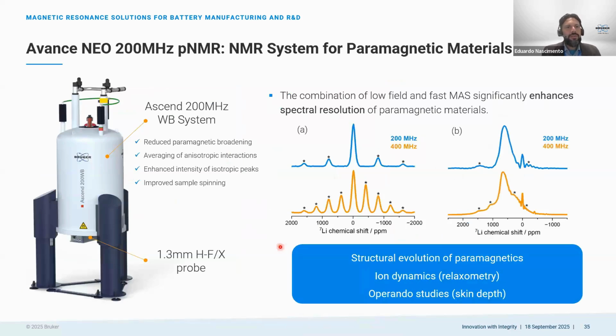Bruker recently launched a new version of the solid-state NMR system, the so-called 200 megahertz. Normally in NMR, we are looking for higher fields, but Bruker launched a lower field instrument. That's because for analyzing paramagnetic substances, the lower fields are more important, since you can decrease the interference. You can see here, for example, that when you go from 400 megahertz to 200 megahertz, the signal is much clearer. So you can easily study the structural evolution of paramagnetics, ion dynamics, and for operando studies as well.